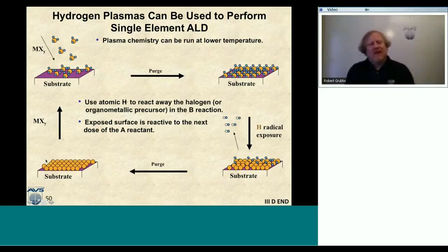Now, this is a difficult way to make these single elements, because of the attenuation problem with delivering hydrogen radicals, and because this surface is so reactive to any oxygen in the reactor that it might oxidize very quickly. So you might end up making the metal oxide, not necessarily the base metal that you want. So those are four different methods on how to make single elements with ALD.